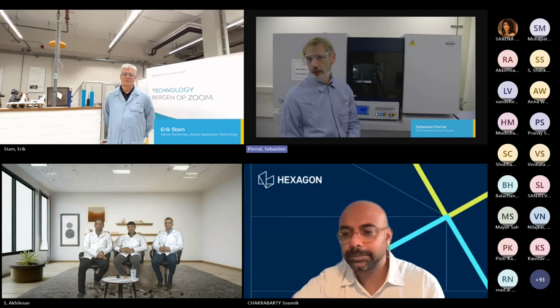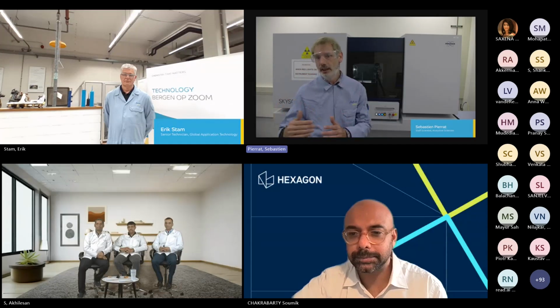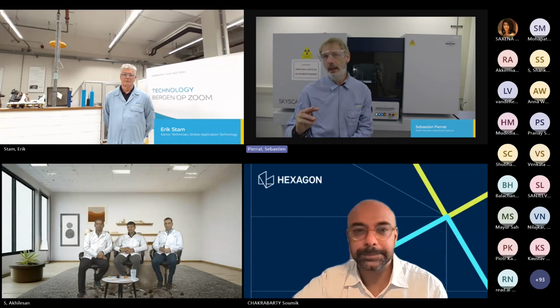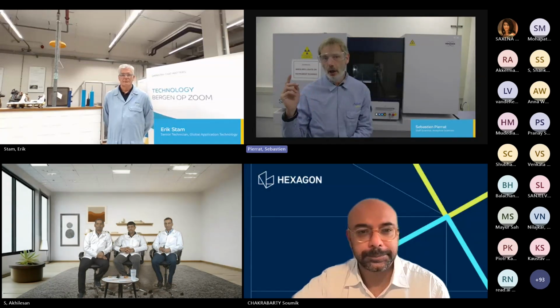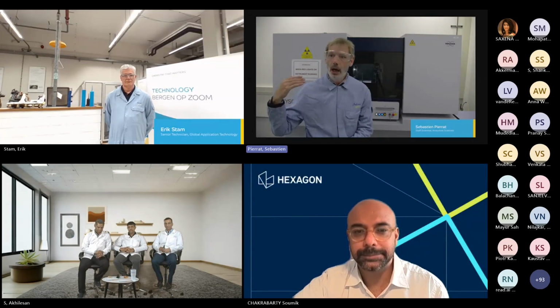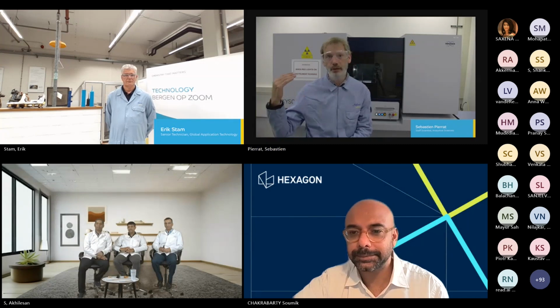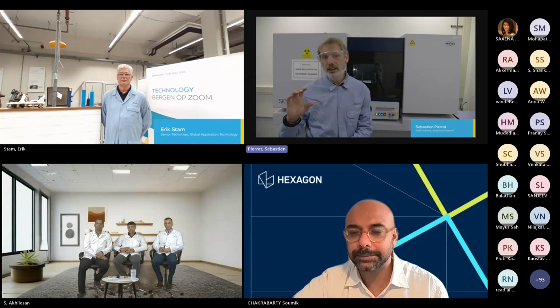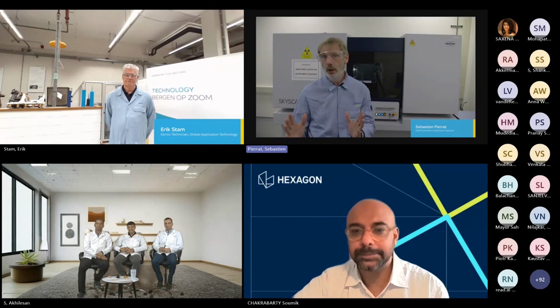In glass filled material, for instance, in order to limit the artifact due to the scattering of the glass fiber, I typically use 6,000 projections. One thing to have in mind here is that the higher the quality is, and the higher the number of averages and the number of projections is, the scanning time drastically increases. We can go from a few hours of scanning time up to a few days. So it's always a threshold optimization between the resolution, the size of the sample, the quality of the images, and the time that is needed for the scanning.